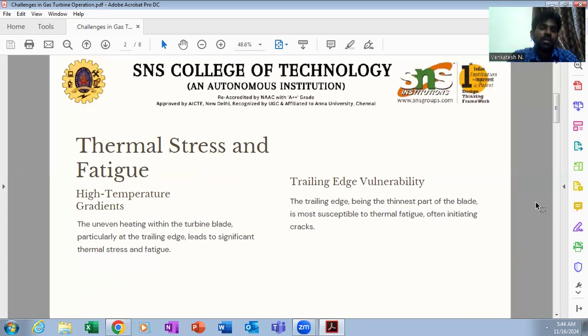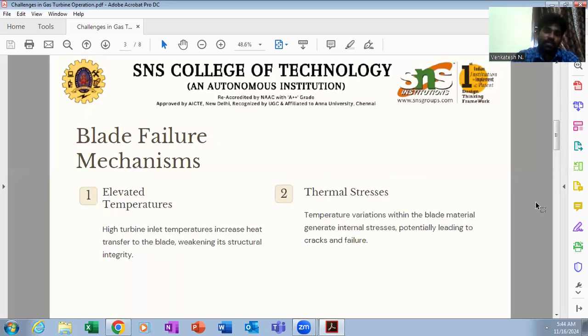A common challenge is thermal stress and fatigue, from high temperature gradients. The uneven heating within the turbine blade, particularly at the trailing edge, leads to significant thermal stress and fatigue. The trailing edge, being the thinnest part of the blade, is most susceptible to thermal fatigue, often initiating cracks.